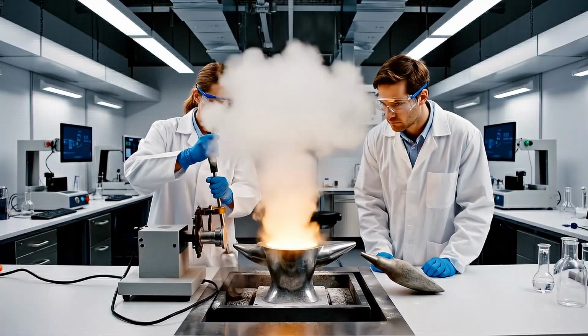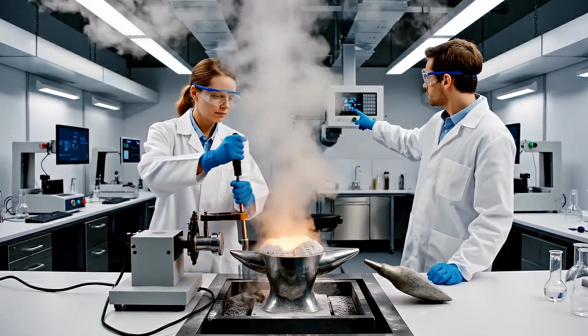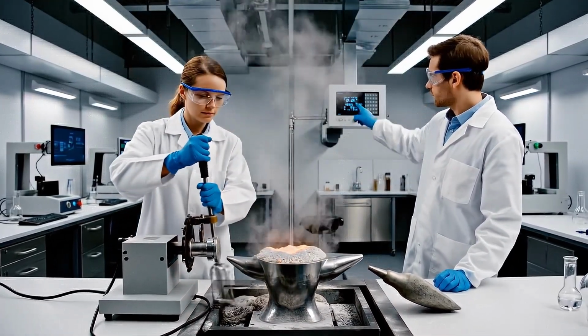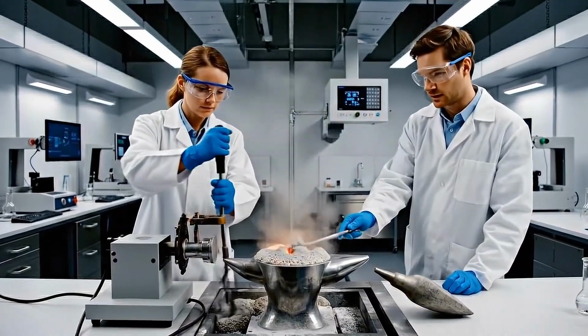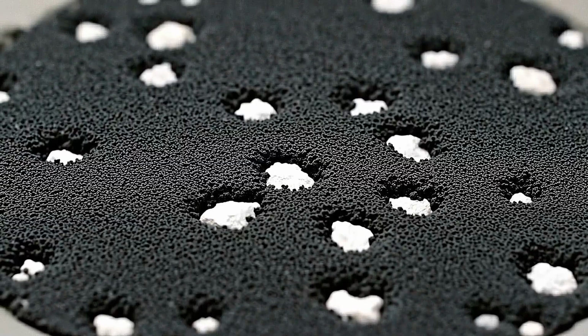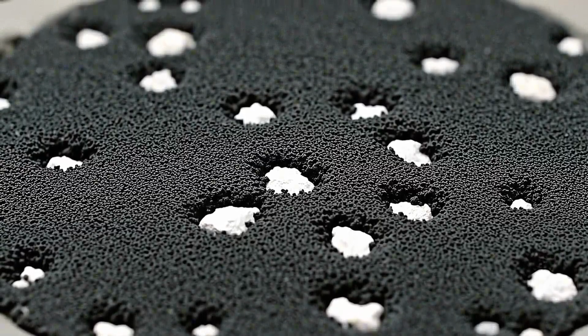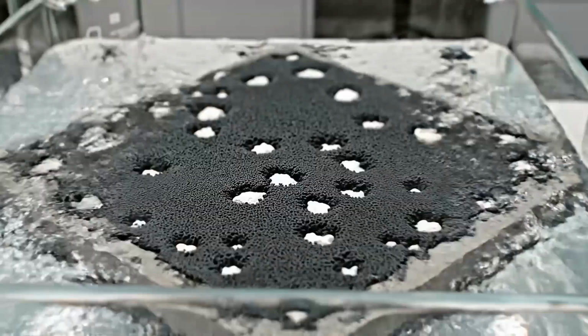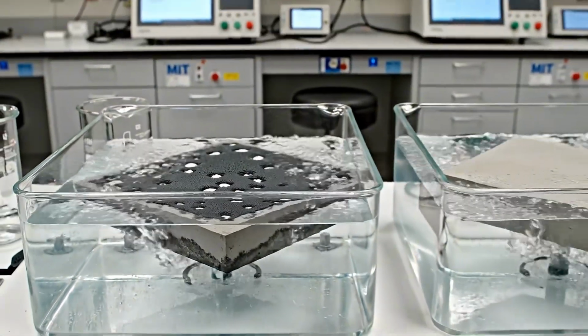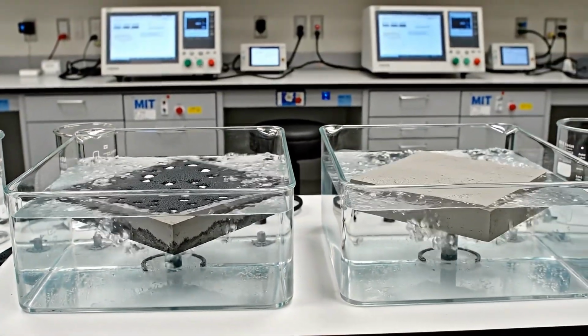These lime clasts, white calcium carbonate and calcium hydroxide inclusions, ranging from sub-millimeter to several centimeters in size, are not evidence of poor mixing. They are the deliberate product of a specific mixing technique that Roman engineers used, and that modern concrete production has entirely abandoned: hot mixing.